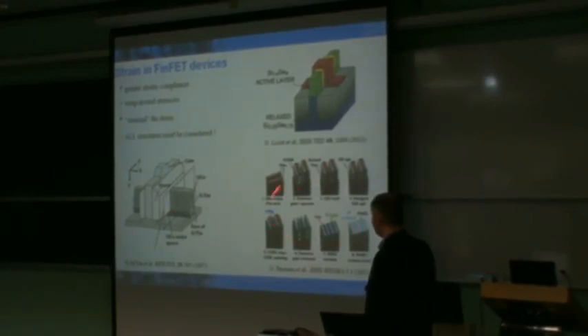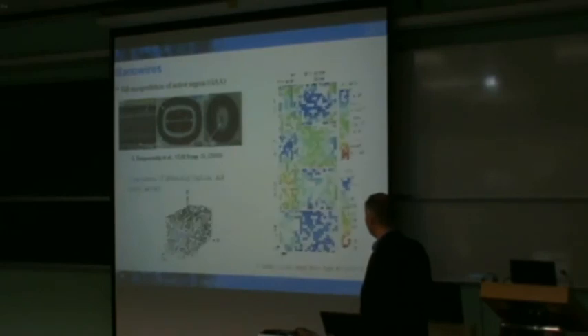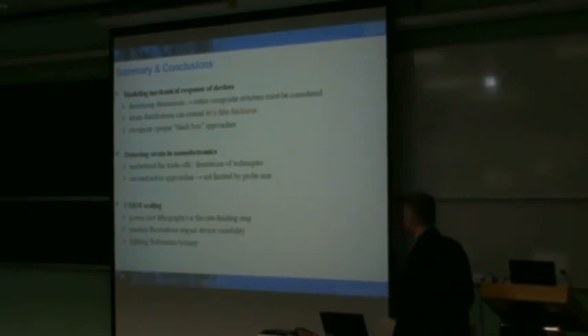And really what I'll just show is this bottom point here, that now we have an extremely compliant structure, either in a fin shape or a nanowire shape, so every aspect of the integration and its impact on these devices has to be incorporated to truly predict what's going on. That's true of the nanowires as well. So with that, I'll conclude. It's clear that with decreasing dimensions, we have to look at these effects. We know that they can extend clearly very large distances, and that's to be expected from elasticity. But it's important that whatever model we use, we recognize its limitations in terms of understanding this.